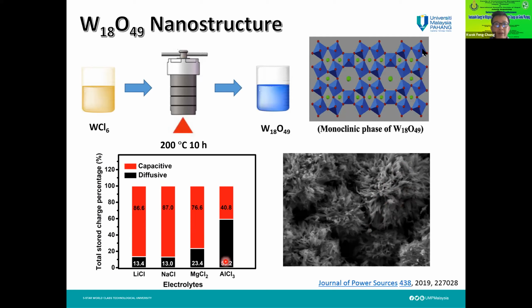Then we find a very interesting behavior. We compare between the electrolytes. We try to put in the lithium, the sodium, the magnesium, and then we try to put in the aluminum. In this case, the black color is the one that we see. How much percentage of your charge storage is actually caused by the capacitive or the diffusive process? Diffusive means that your ion can penetrate and diffuse in your crystal structure. We can see that there is a very high percentage of diffusive behavior for the aluminum chloride in the tungsten oxide.